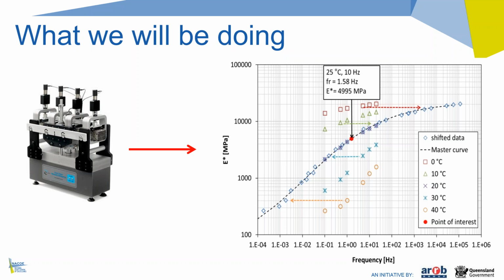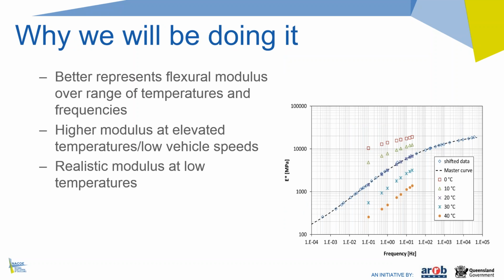So we run a set of frequency tests at every temperature, and then once we've characterized the materials over a range of temperature and frequencies, we shift those results in the frequency space to form a continuous master curve. And by doing that shift, we then have the relationship between temperature and frequency, and we can convert between the two, and we can use this master curve to predict the design modulus at any combination of temperature and load frequency. So that is the master curve in a nutshell. I'll be going through the construction of it a little bit later, although not in much detail. So if you lose track, don't worry, the test method in the tech note explains exactly the steps that are involved in this.